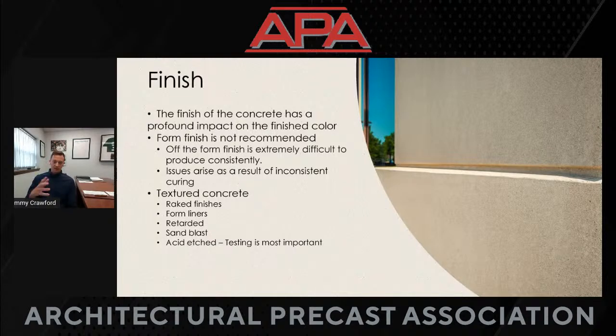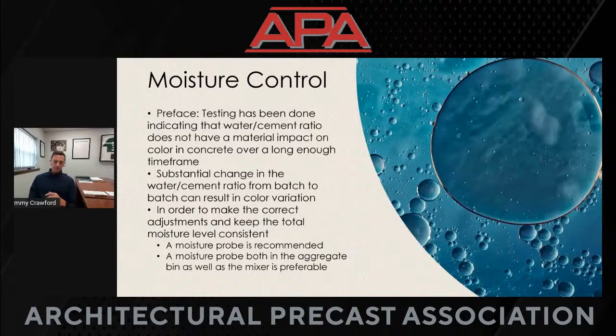Finish, as I was just saying in the question, the finish of concrete has a profound impact on the color. Form finish, I strongly recommend not doing a form finish. A lot of the paste on the surface of the concrete is going to have extreme color variation. We recommend pretty much any textured finish over a form finish. Raked, form liner, retarded, sandblasted, acid etched. Testing with an acid etched finish is important. You want to be consistent with your etching. Excessive etching is going to cause color variation as opposed to a light etch.